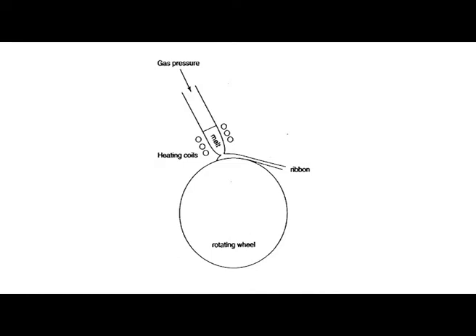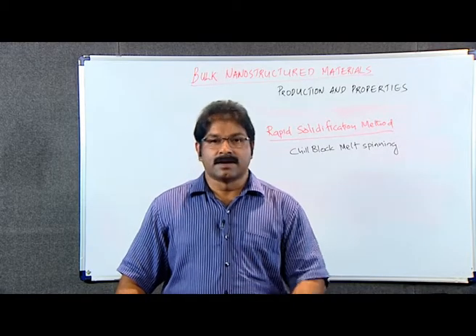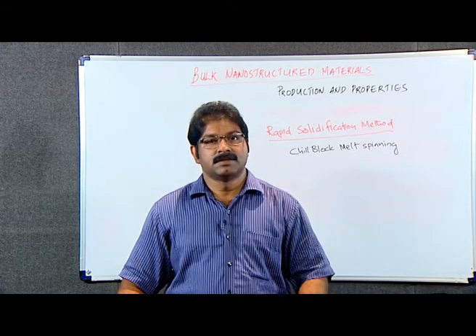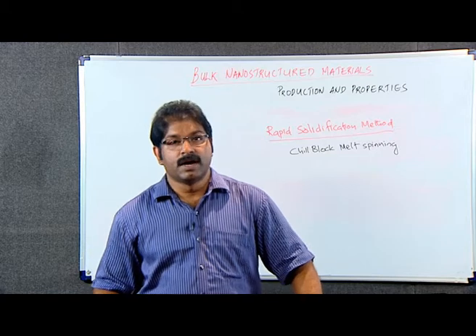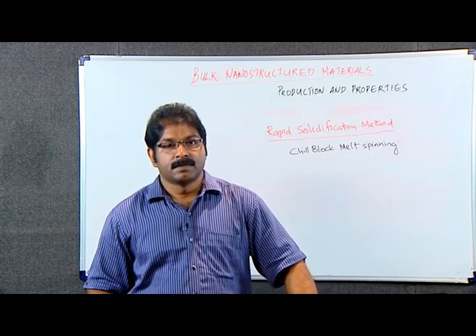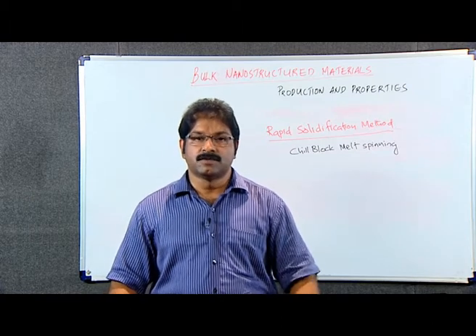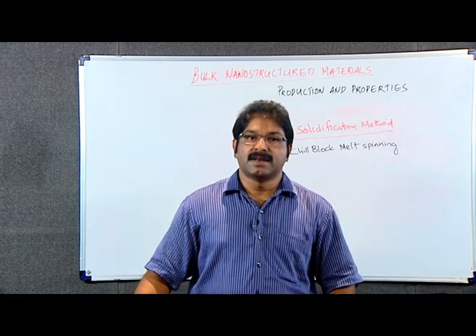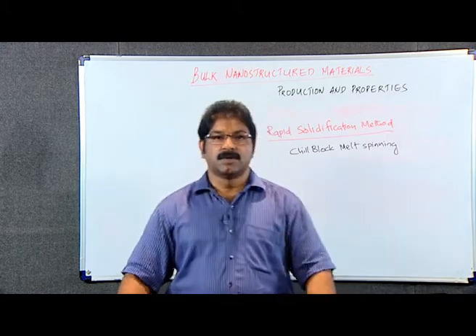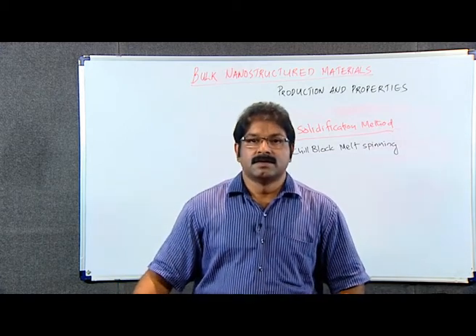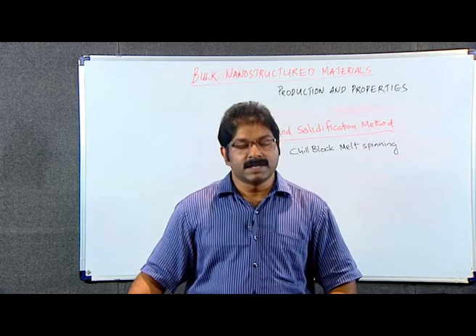Look at the picture. In this method, radio frequency heating coils or eddy current coils are used to melt a metal. We know that when a radio frequency current is passed through a coil, eddy currents are generated in the metal which is placed inside the coil. This eddy current heats up the metal and melts the metal. The melt is then forced through a nozzle to form a liquid stream. This stream is continuously sprayed over the surface of a rotating metal drum under an inert gas atmosphere. This process produces thin strips of metal ranging from 10 to 100 micron thickness.